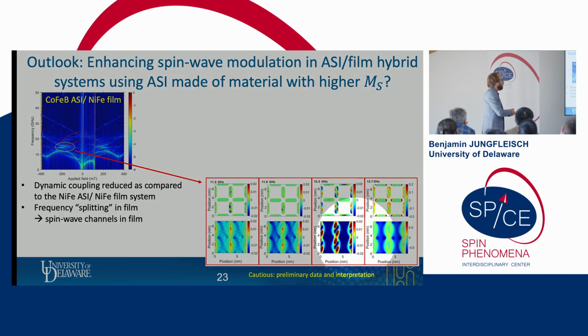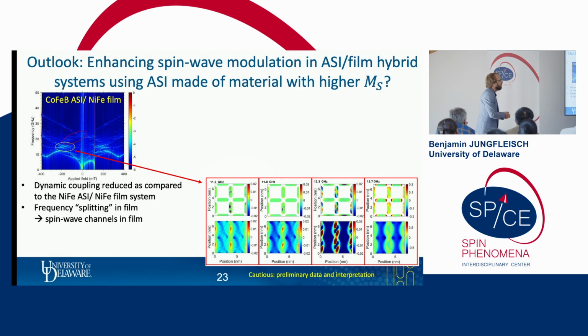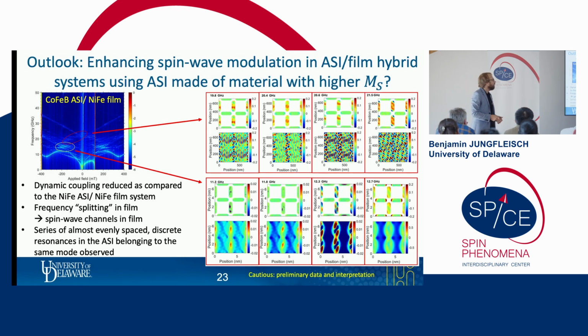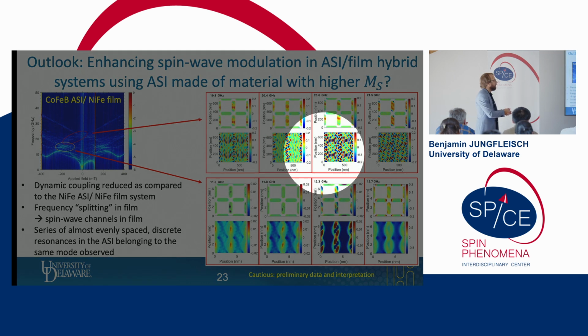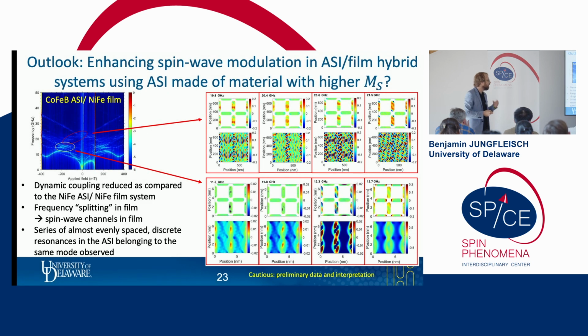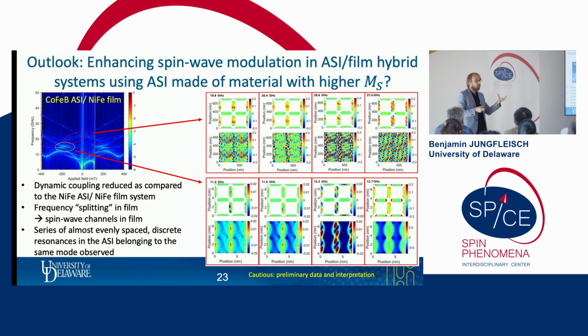And in the artificial spin-ice layer, we basically see no dynamics at all. There's something similar happening for the artificial spin-ice system at higher frequencies. Again, the film layer here shows basically just noise, but we see a series of almost evenly spaced discrete resonances in the artificial spin-ice layer. And interestingly, this belongs to the same kind of mode with the same kind of nodal structure. So this is some preliminary data.